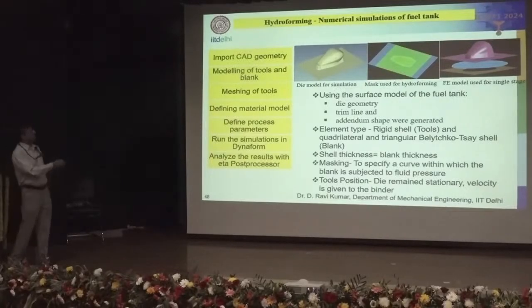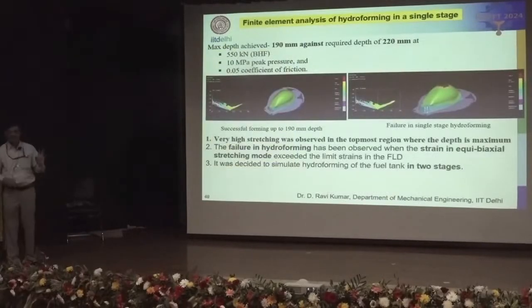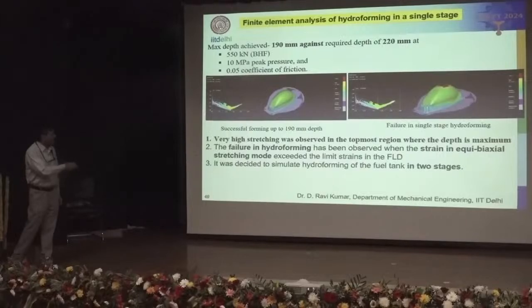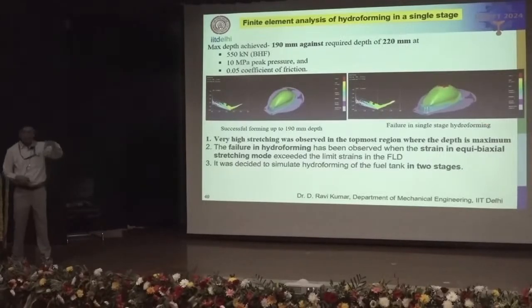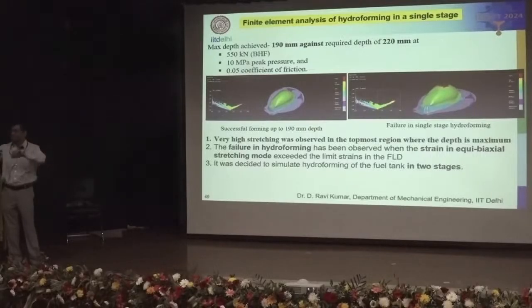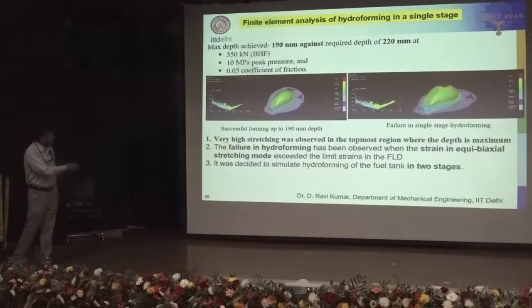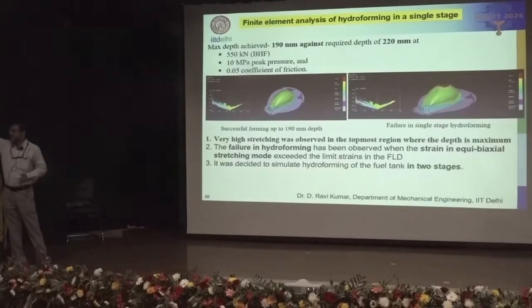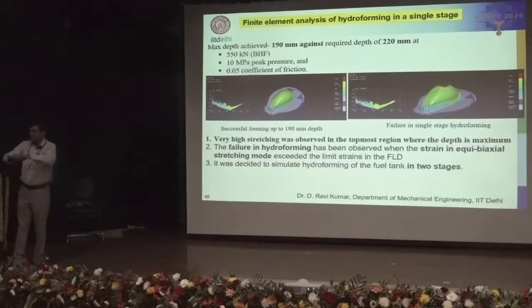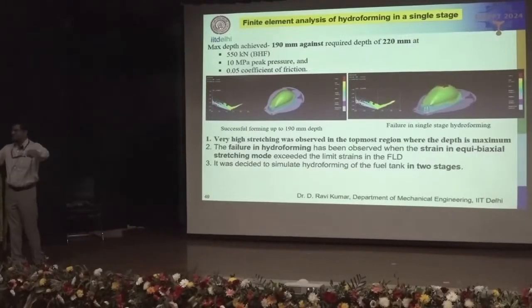So we have found out that in one single stage of hydroforming, it is not possible to achieve the entire depth. Here we can see the failure in single stage hydroforming. You can clearly see the failure at the location where the depth is maximum. That is where the material gets stretched biaxially. And here we can clearly see that the strain path is towards equibiaxial tension. Because this is fluid pressure, there is no friction.